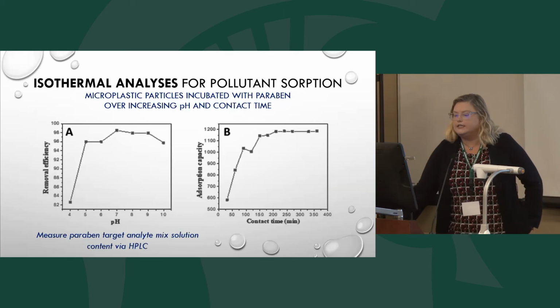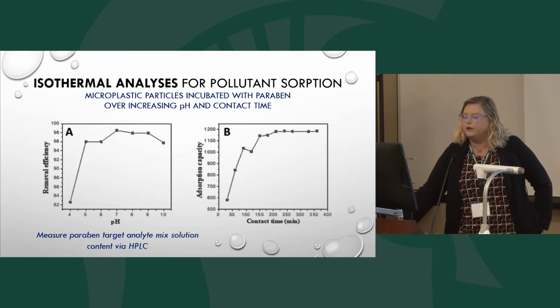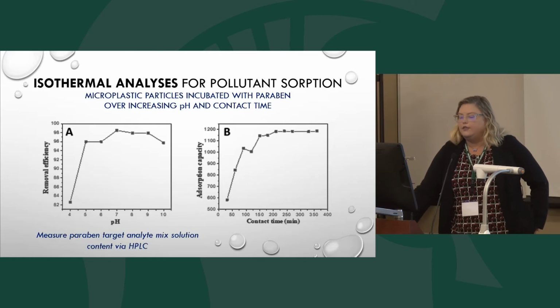And isothermal analysis, these are some of the graphs that we produce when we change the pH of the microplastics in solution. We measure the paraben as a target analyte. It's a standard that you can buy from Sigma Aldrich, and that's what we put in water. And then we're looking for the paraben concentration using HPLC at different pHs of the solution to look for the removal efficacy. And then we also looked at contact time, for how long those microplastics are stirring in the vial with the paraben in water. And we see over time the amount of paraben associated with the microplastics increases.